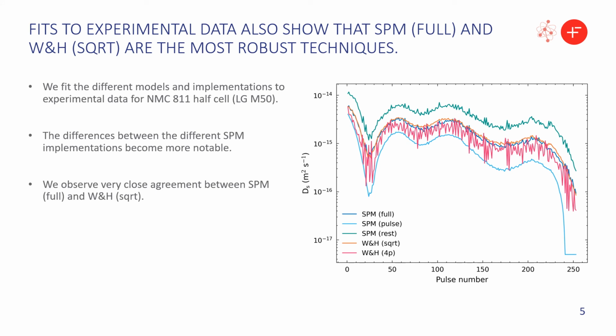And on the other hand, we see that here, maybe that's unexpected, that the SPM full and the Weppner and Huggins square root perform very similarly. That's probably because we are on the lower range of the diffusion coefficients, 10 to the minus 15 and lower, and therefore here we would expect the two models to perform very similarly. So that's interesting. And despite they perform very similarly, we still recommend using the SPM full because it's more general. One of the main challenges here is how to calculate the derivative of the OCV, because that can be quite noisy. In fact, that's why the 4-point method is noisy, because it just uses finite differences. What we do here, for the other methods, is fit a spline to the OCV, and then take the derivative of that spline as the derivative of our OCV.